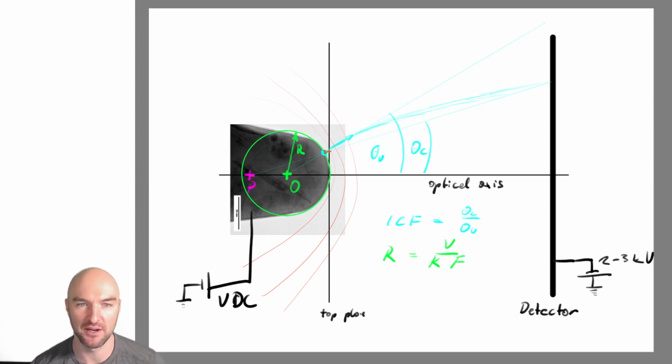But what they found is that if you look at, for example, the crystallographic poles in field desorption maps, their positions change during the experiment. Essentially, the image compression decreases as the evaporation voltage goes up. They did that using crystallographic poles, and came up with a nice curve of how to correct that. I did that a little bit differently, but let me show you the nice videos of how that actually looks.